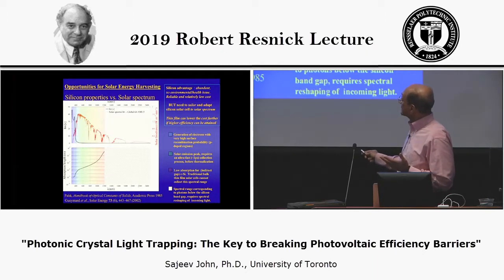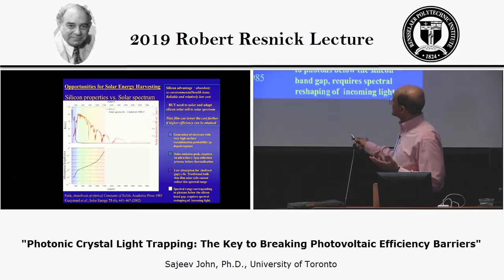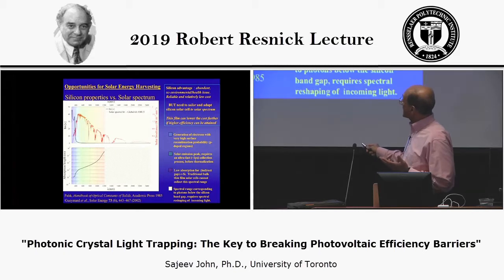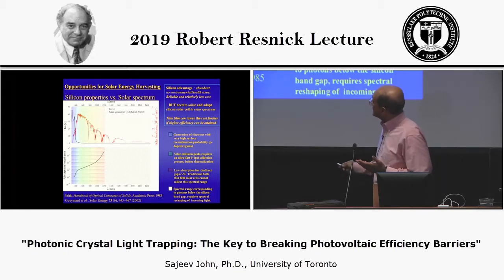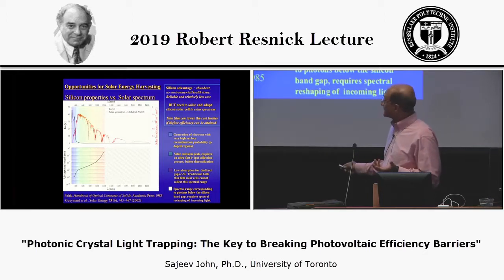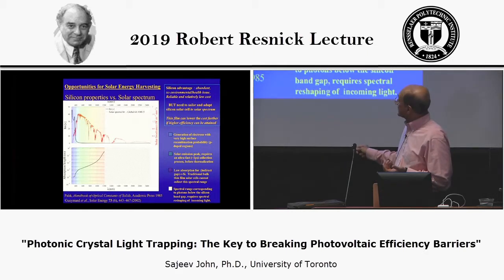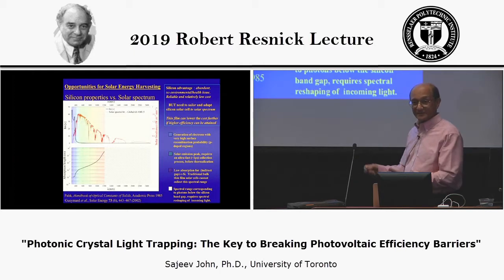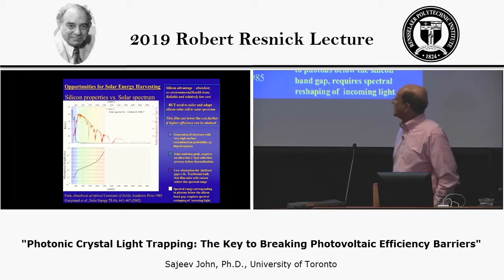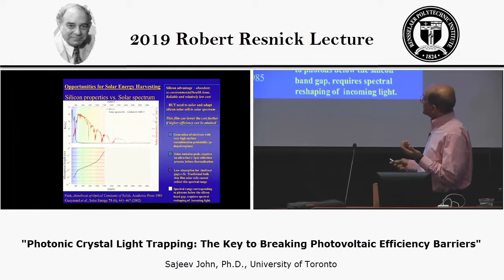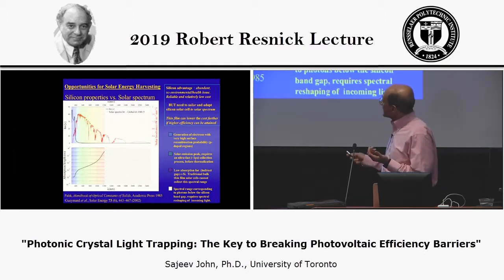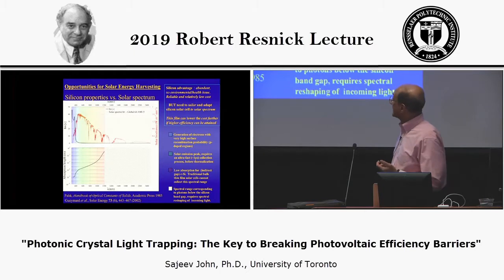But as you go to longer wavelengths, you get less and less absorption, especially in this indirect band gap region, where if I replot this imaginary part as an effective absorption length, you start with an absorption length down here in the blue region of tens of nanometers, and over here you're on the scale of tens of centimeters, and no one's going to make a cell that thick. And so the ideal is to have some light trapping mechanism that will allow you to absorb as much of this spectrum as you can over the entire range of 300 to 1200 nanometers.